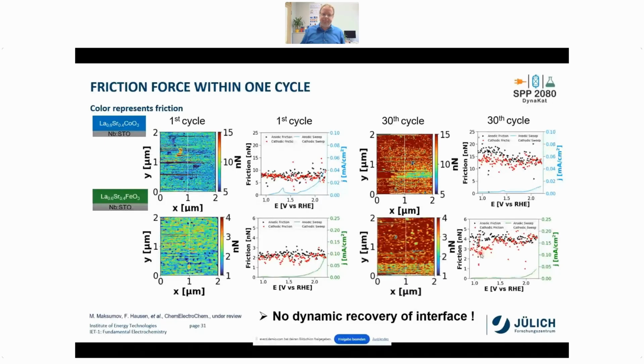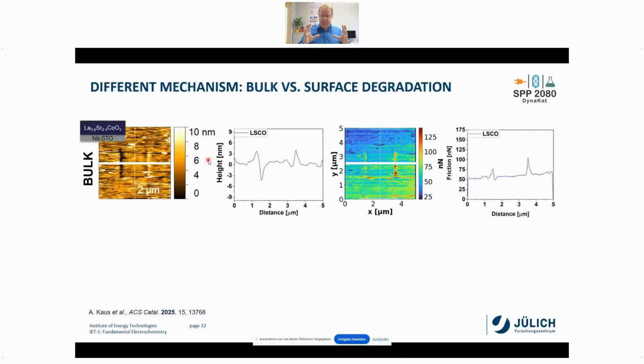So it was shown by spectroscopy that the degradation mechanisms of both materials are a bit different, and we want to understand a bit more. So we zoomed out, and I can just recommend to all of you, when you record friction force images, so you were in contact with your AFM tip, that you zoom out and see if you produced any damage of the material, but not just to probe, oh, you have an artifact, but also to learn something from that.